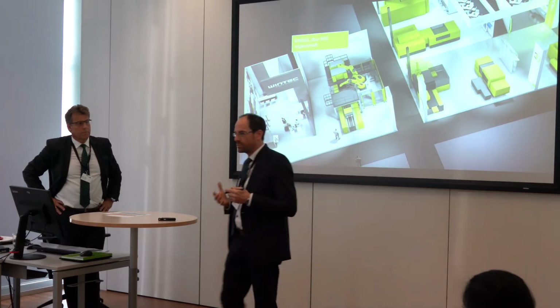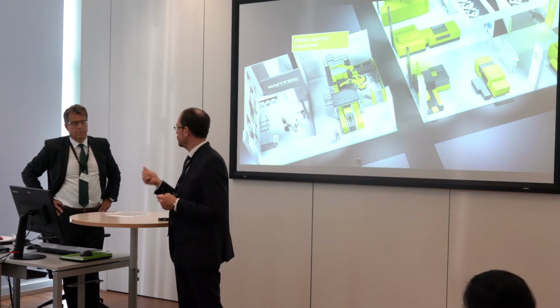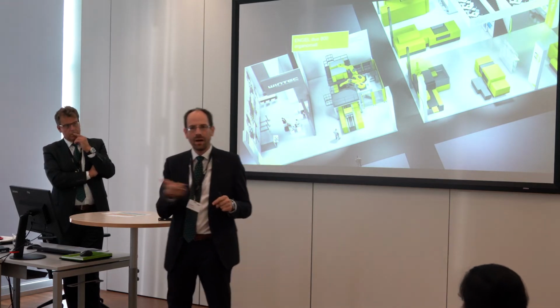There is a strong trend in the industry to switch from curing, thermosetting composite solutions to thermoplastic solutions, and the reason is that we are in a different field of productivity. At Engel, we are well known for highly productive injection molding machines, and molding normally takes place in less than 1 minute, 30, 40, 50 seconds of cycle time. This was never achieved with a composite material until the thermoplastic solutions showed up, and with thermoplastics we are able to produce parts with the same productivity as in an injection molding process.